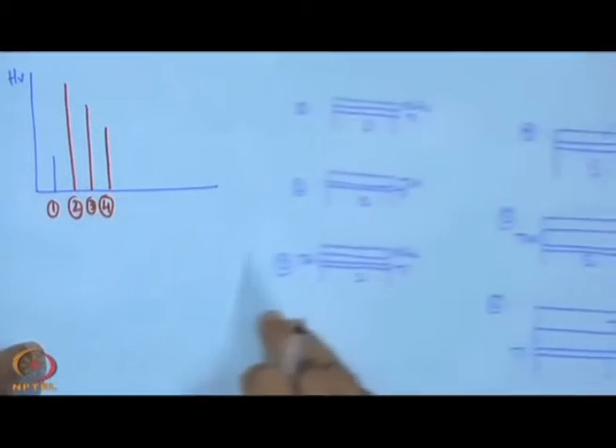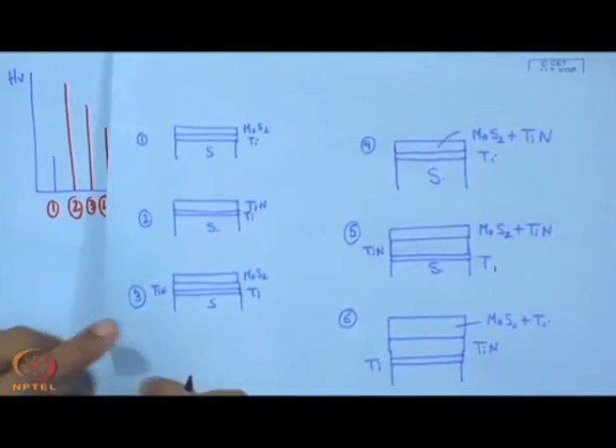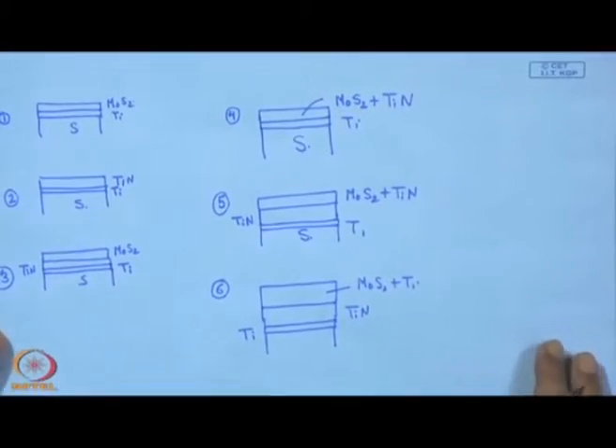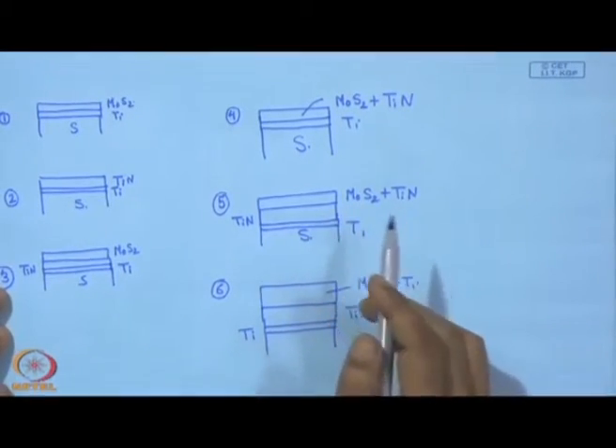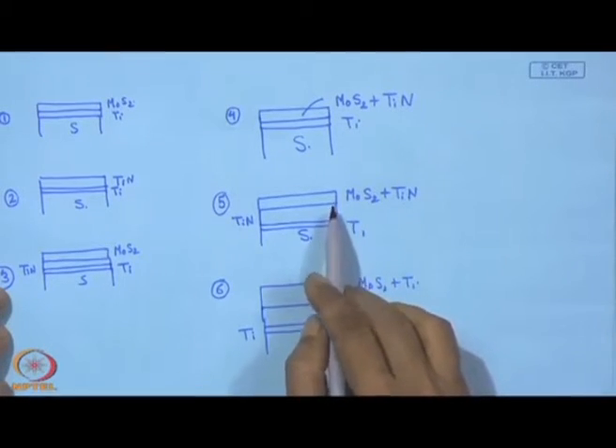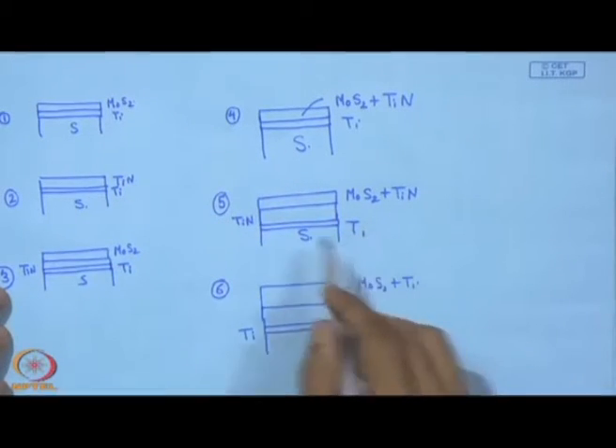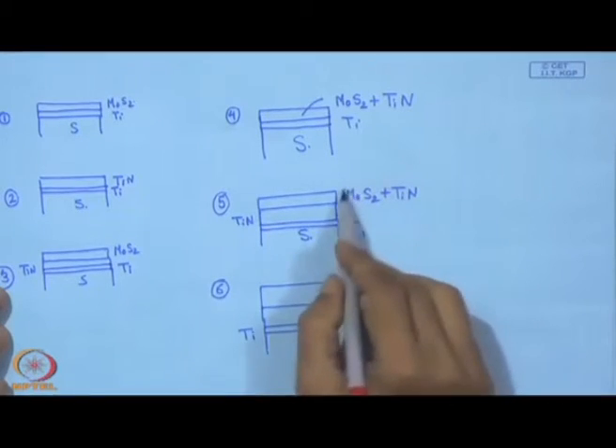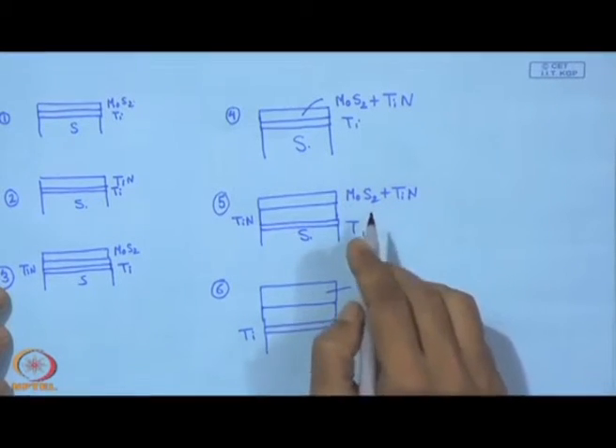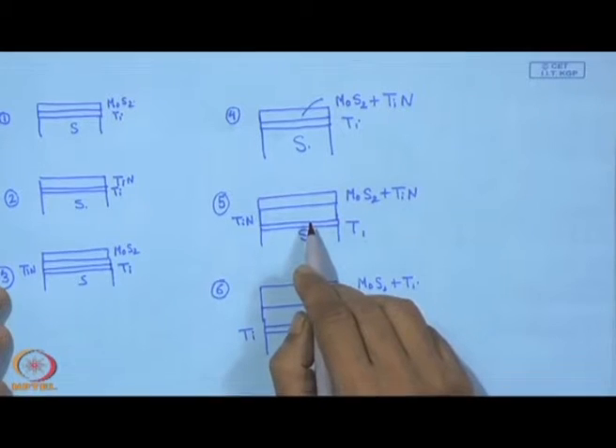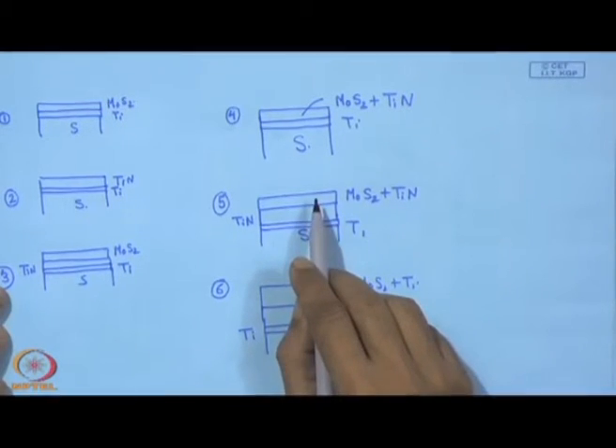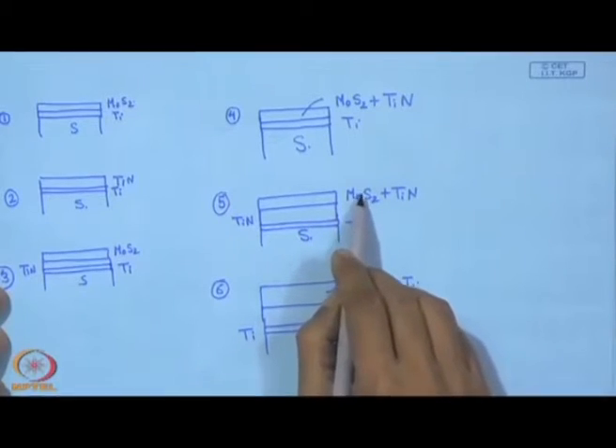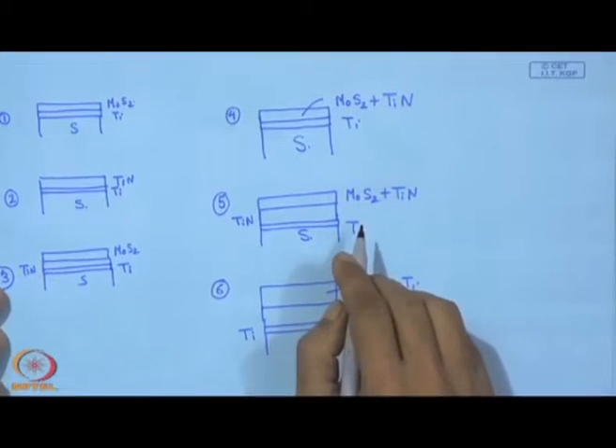and then we have number 5, and with this number 5 we can have a quick look here, that it distinguishes itself from the rest of the things, because in this case we have a composite architecture at the top, but we have a supporting layer of TiN. So, this is one of the very hard coatings, and in this case we have TiN and at the same time at the top MoS2 plus TiN.